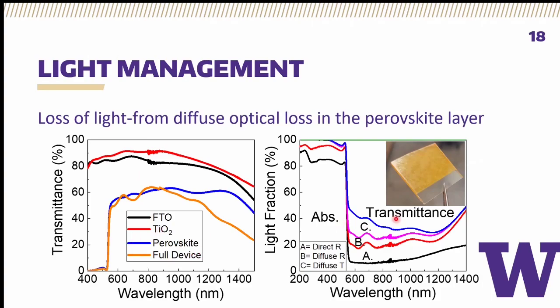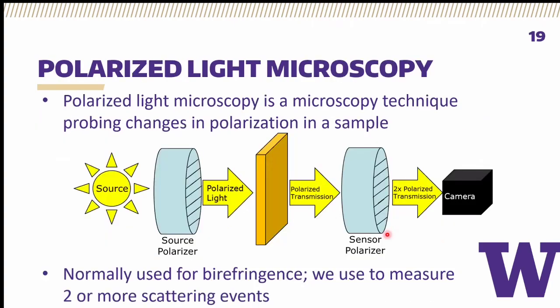Taking the perovskite layer, which has this weird glossy look to it, atypical of perovskites that have narrower band gap, to a diffuse reflectance accessory, we saw that we had a lot of scattering processes contributing to a significant, in fact unacceptably high, portion of the transmittance loss in these devices. This was very unfortunate and something we were thinking about characterizing, because if others were to also try to use this material in a tandem, this is an important consideration they'd have to wrestle with.